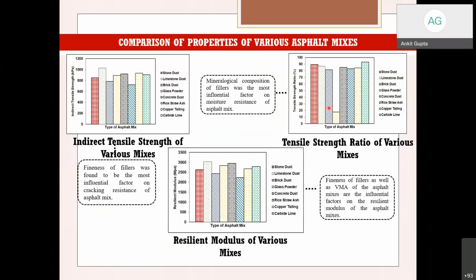Now all these values are shown as histograms for the indirect tensile strength and the resilient modulus. These resilient modulus values we tried to find out, not from our lab, but from the lab at IIT Kharagpur. And this is the stone dust. You will see that the resilient modulus of all the waste modified mixes is of a comparable nature. Only for the rice straw ash is the resilient modulus very low as compared to the conventional stone dust. The rest are all in a similar range.